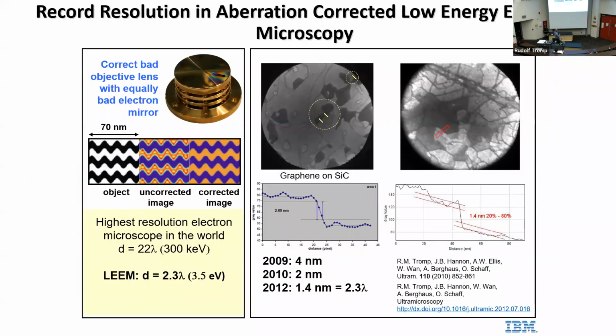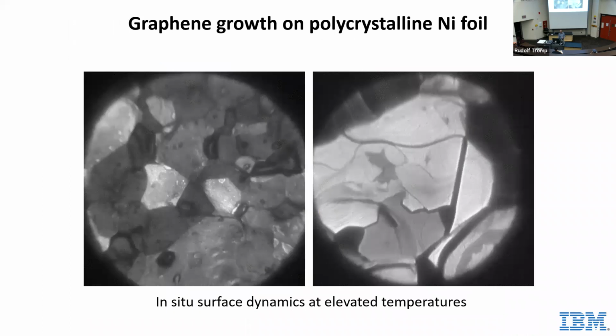So with this, we get a spatial resolution after 2 years of tuning of about 1.4 nanometers, right? You see 2.3 times the wavelength of the electron. The best TEMs get something like 20 times the wavelength of the electron. Of course, those wavelengths are much shorter, but nonetheless, in this LEEM, where a wavelength is really quite large, in the order of a fraction of a nanometer, we get very close to what you would think is the diffraction limit, should be the diffraction limit.